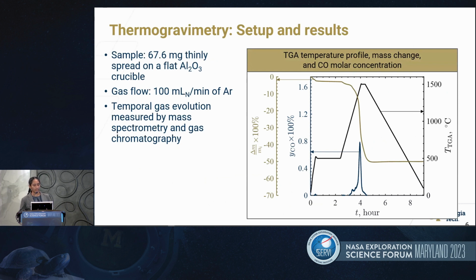Moving on to thermogravimetry, about 68 milligrams of sample was spread on an alumina crucible, and the experiment chamber was filled with 100 milliliters per minute of argon flow. The sample heating profile is shown in the plot in the black line. The sample was first heated to 500 Celsius for 2 hours to remove moisture, and then to 1500 Celsius before cooling down. The temporal gas evolution was measured using mass spectrometry and gas chromatography.